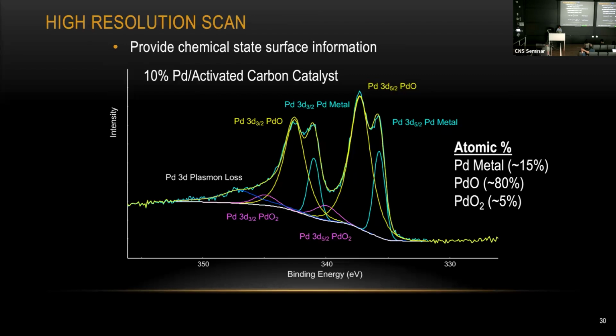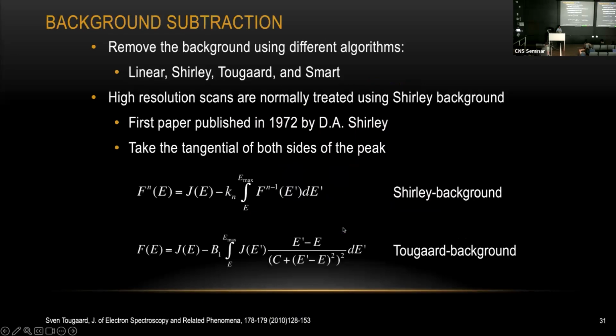So how does XPS give you all this quantification information? The first thing we need to do is subtract the background. When we work on XPS data, we only take care of the area underneath your intensity, so we need to subtract the background first. There are different kinds of mathematical algorithms you can use to subtract your background. Mostly people use linear, Shirley, and Tougaard. They're just three different background subtractions people use over time. Here, we are working with a Thermo Scientific machine, and they have another algorithm called the SMART algorithm. That's simply an improved version of Shirley.